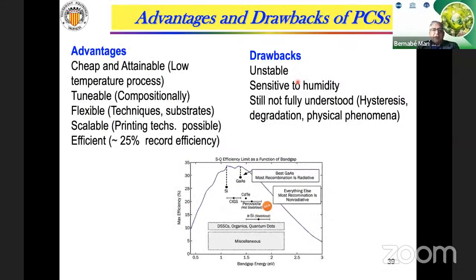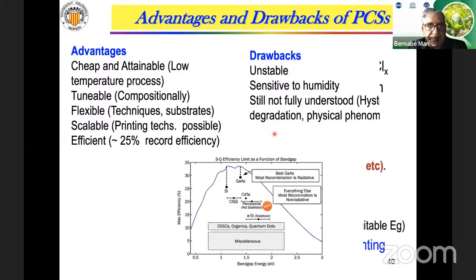Well, the advantage of the materials is that they are cheap and attainable because the processes are done at low temperature. We can tune the composition. We can use flexible substrates. It's also scalable, and the efficiency is very, very good. Well, the drawbacks are that the materials are very sensitive to humidity. They are unstable, and there are some phenomena of hysteresis which are not well understood.